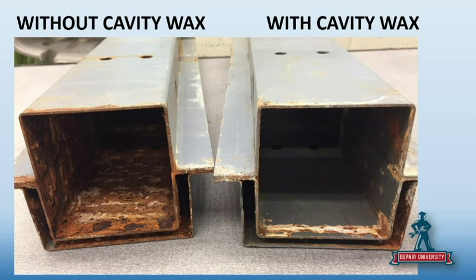Yeah, this went through a salt spray chamber test here, and the one on the left, keep in mind, it's also galvanized. Right. And look at how aggressive that salt spray test is. It will rust right through that metal. But if you look at the one on the right, that's protected with cavity wax, and it's probably 3 coats. It's very well protected. The only corrosion you see is what started to creep in from the outside. So very well protected.